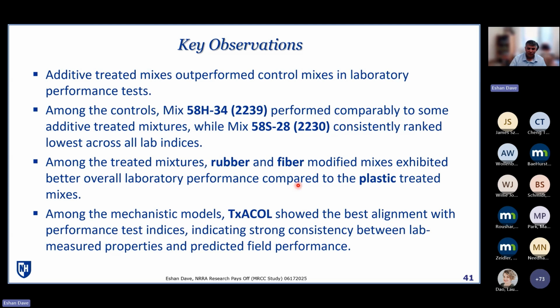And then lastly, between different mechanistic models, if we compare the results of these different indices, whether it's the fracture energy from DCT or flexibility index or whatever you may have, where we saw the most consistent matching was with the TxACOL, which had the best alignment between the performance test indices and the lab results. Now, keep in mind, all of this is synthetic in the sense that we are only comparing models to test result properties, not the field performance.